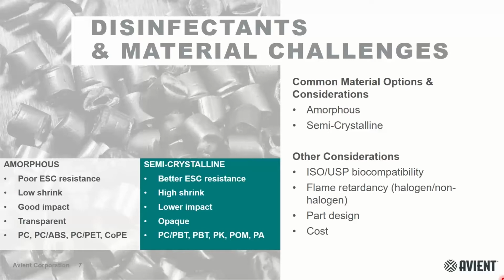Some of the benefits of an amorphous material are that they exhibit low shrink rates. They also tend to have good impact, and they can be made transparent. So a few examples include PC, PC/ABS, copolyesters. And then the semi-crystalline materials, as I mentioned, have better environmental stress cracking resistance, which is imparted by the crystallinity. It provides a barrier. It also reduces chain mobility. However, the drawback because of this crystallinity is that they tend to show higher shrink, so it's something that has to be planned for. They also tend to show a little bit lower impact, and they're mostly opaque. Some examples here are PC/PBT, where the PBT is primarily bringing the crystallinity, polyketone, POM, and also other polyamides.